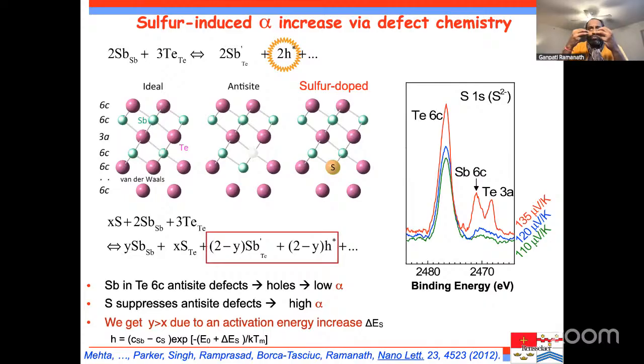In our case of sulfur doping, which we found serendipitously, we had no idea sulfur was getting into this material. We were just using a sulfur-terminated molecule to make these materials. And then when we characterized this, we found that sulfur is getting into it, and we found it's doing magic.